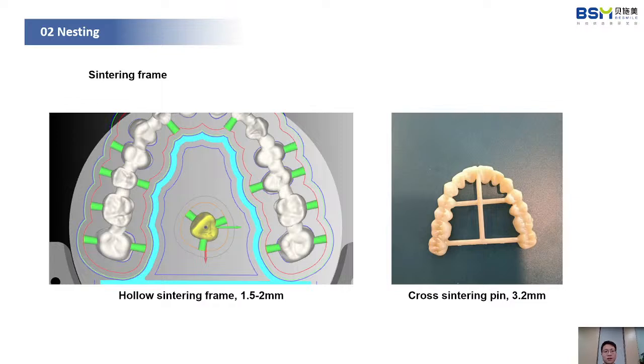Okay, and then in the nesting software, we can also change the sintering frame. And now we have two types of the sintering frame recommended. The left one is a traditional one. It's a hollow sintering frame like this. For this kind of sintering frame, the thickness is about 1.5 millimeter to 2 millimeter. And the thickness of the sintering frame is very close to the thickness of the crown. So it can ensure the bridge and the sintering frame have an even shrinkage during the sintering and avoid some crack problem.